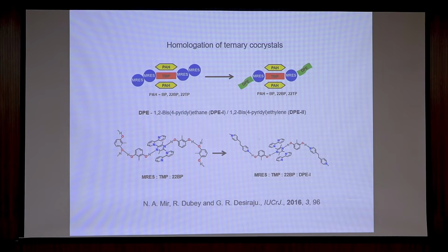So we actually got 4 in one crystal, and we not only got 1, we got about 30-35 quaternary co-crystals where they are all stoichiometric. A few groups have made 1 or 2 after that, but still nobody can catch us in terms of the number of stoichiometric quaternaries that we made. This is quite tough, I can tell you.